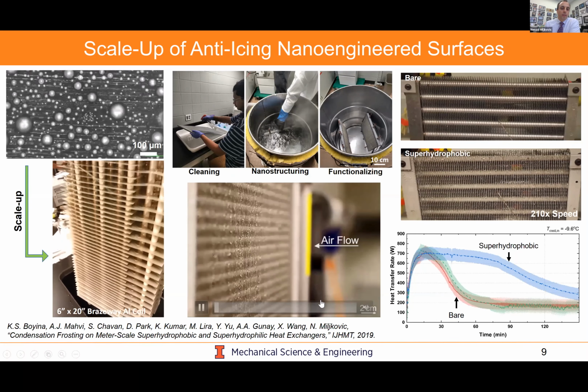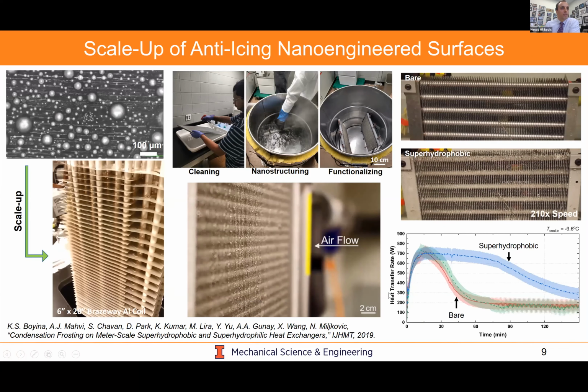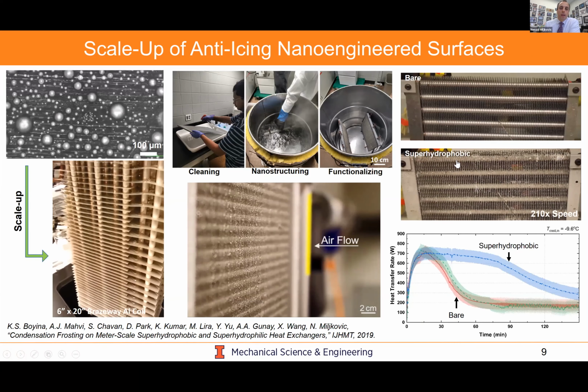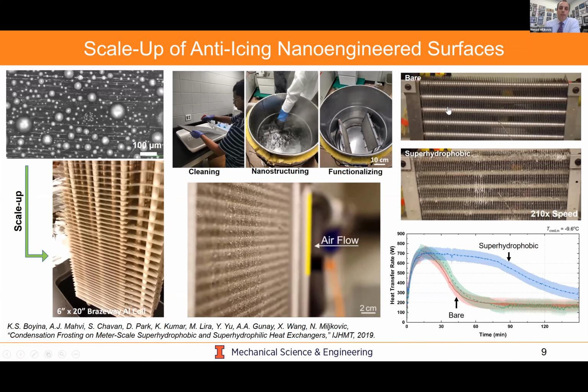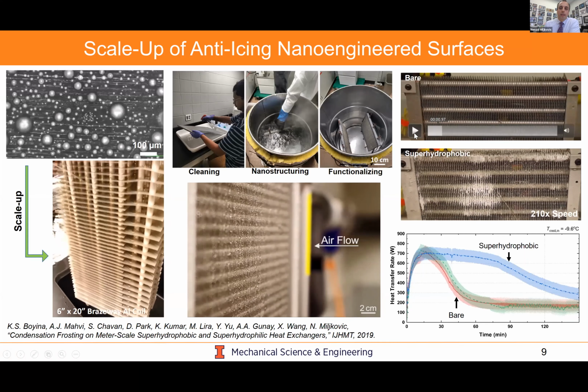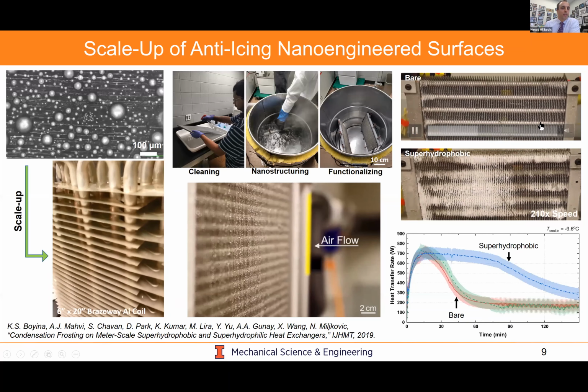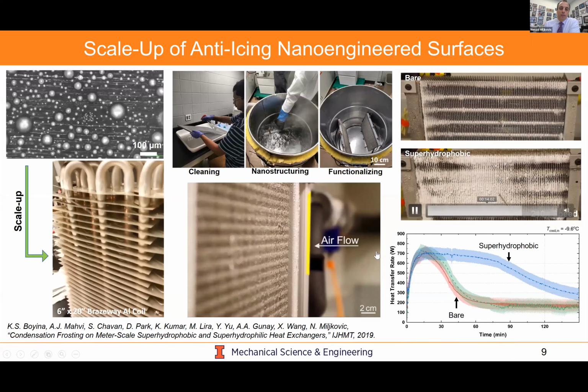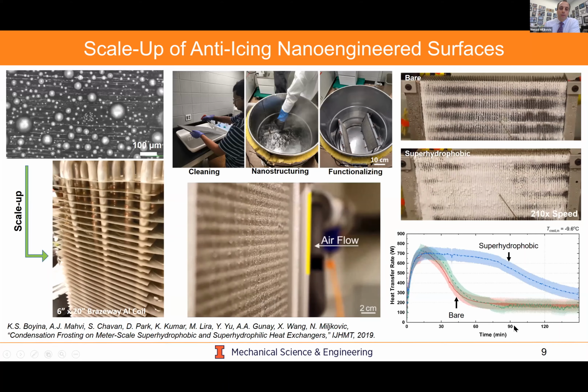So we then instrument these both in quiescent and in wind tunnel conditions. And we can then clearly demonstrate the enhanced performance and delayed de-icing when compared to a bare heat exchanger on the order of 3x delay in terms of time. You could also see this down here with the heat transfer rate as a function of time.